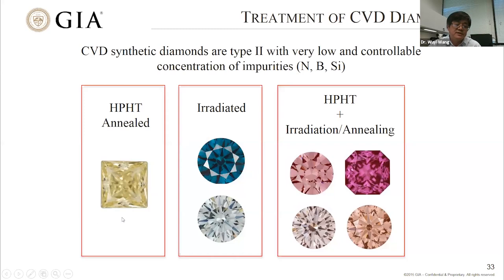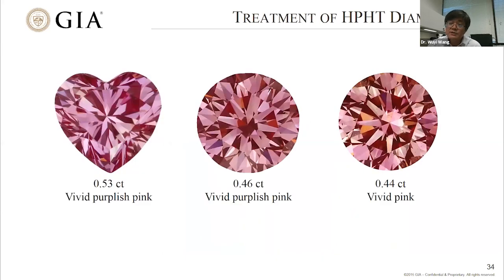HPHT annealing could turn some CVD diamonds to yellow color, very similar to CVD yellow, and it could be irradiated to blue, different saturations of a blue color. But if they are HPHT annealed plus irradiation and annealing, we can generate different saturations of a pink color in CVD diamond. Quite often, we can see this type of treated CVD diamond in the trade. And the treatment can also be applied to HPHT synthetic diamond, HPHT lab-grown diamonds. The 3 diamonds I show here are all HPHT lab-grown diamonds that were irradiated and annealed, of course very important to start with a suitable concentration of isolated nitrogen, irradiated, annealed, and turned to different saturations of pink color.